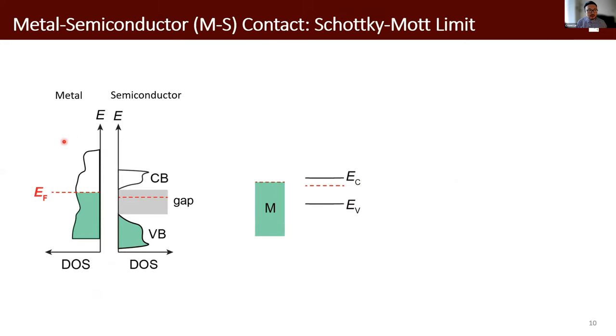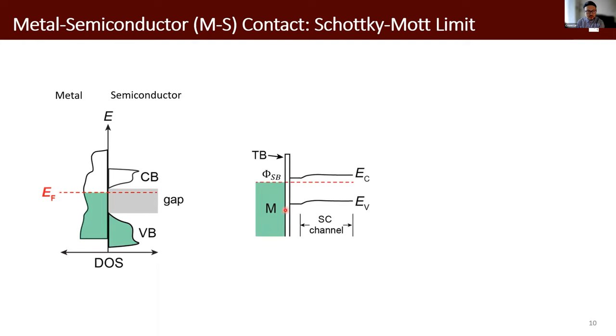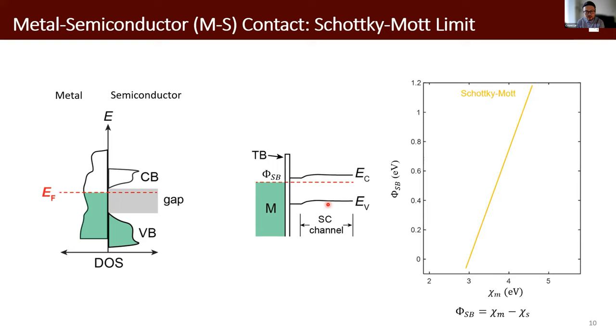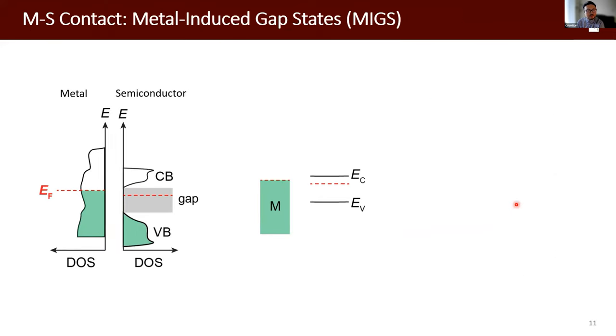So in an ideal case, when the metal and the semiconductor are in contact with each other, the only thing that happens should be charge transfer. When they are in contact, the Fermi level should be the same across the entire junction, and that leads to a Schottky barrier at the interface. In the ideal case, the Schottky barrier height would be just the difference between the work function of the metal and the electron affinity of the semiconductor. If we plot this trend, it looks like a linear curve with a slope of one.